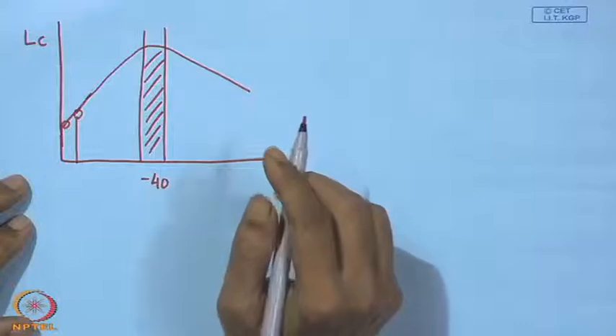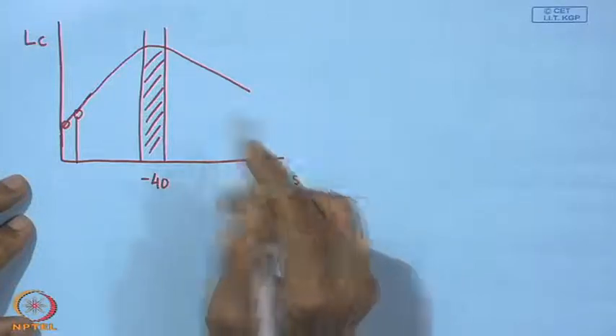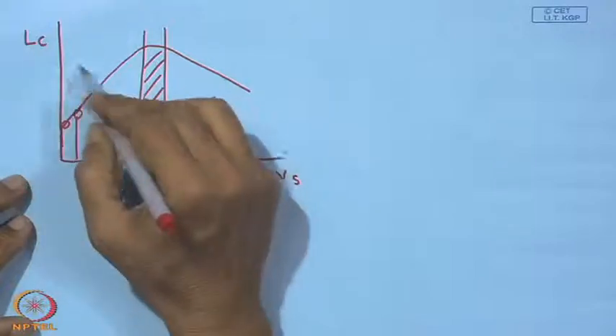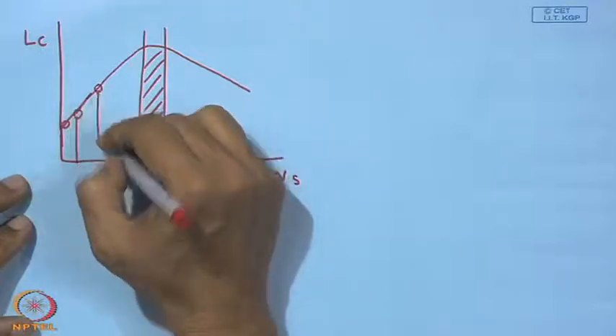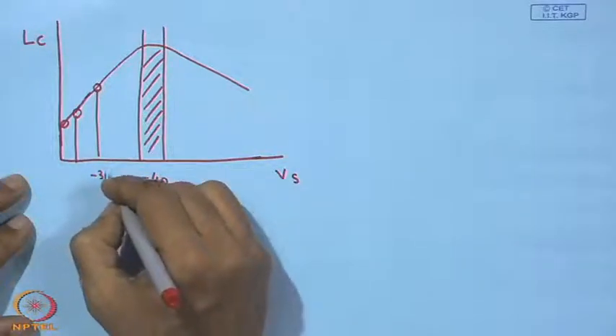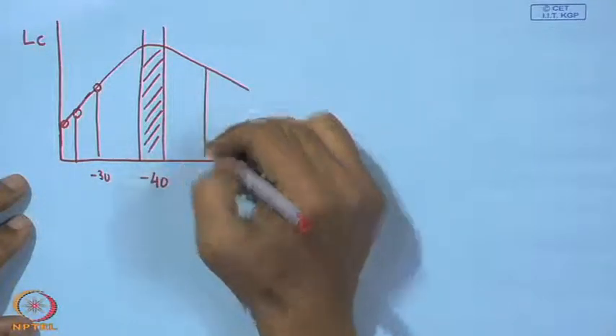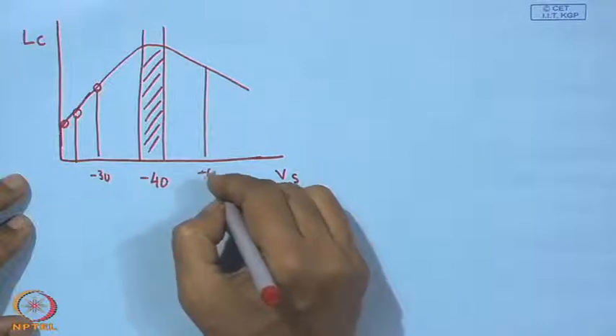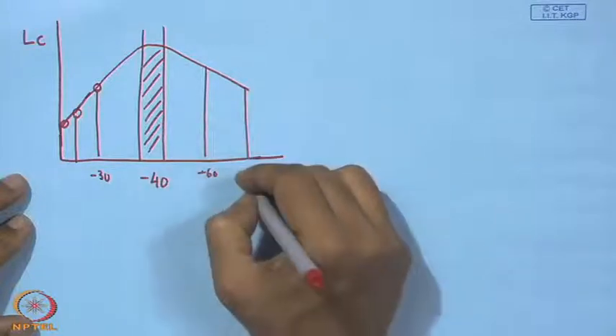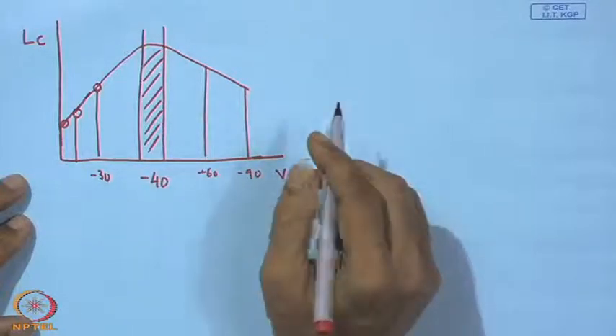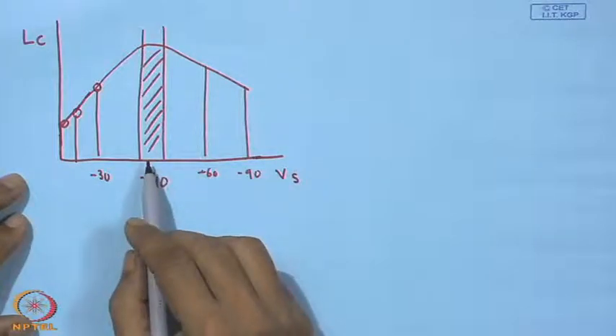So, this is about 0 volt, where we have one of the lowest LC value, that means the critical adhesion strength, and this is maybe around minus 30, but on this side it is actually minus 60, and this is going to be minus 90. So, what happens in this case?